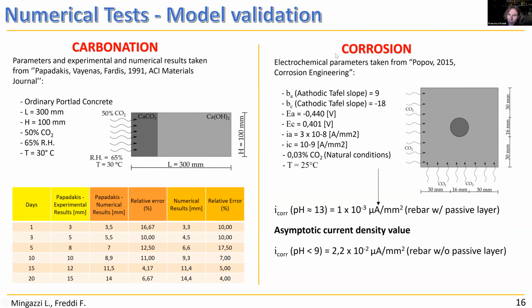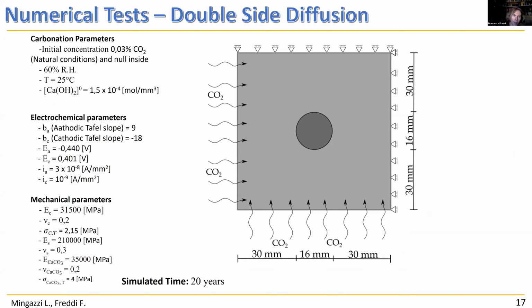After that, we try to see if the corrosion density that we obtain is in agreement with the results obtained from literature via experimental results. And so we have found that with our approach, that is only based on electrochemical equations, we catch correctly the asymptotic current density value as the corrosion process evolves.